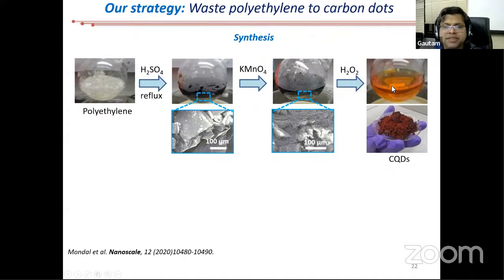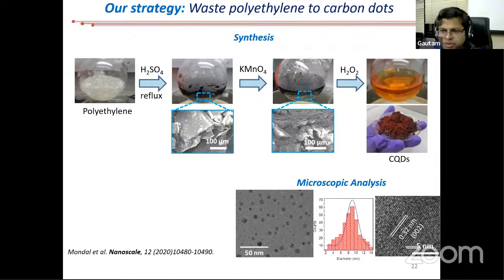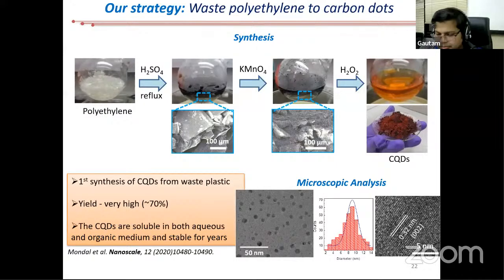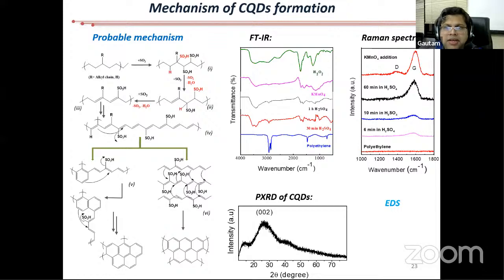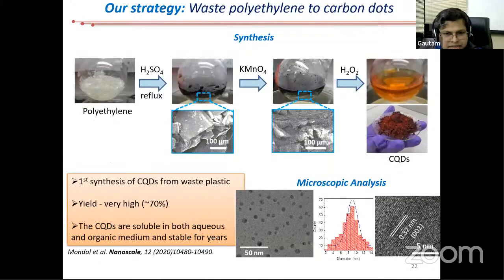It remains there. Okay, but you can remove it from there and you get these carbon dot particles in large quantities. And I showed you that this is about, say, 5 to 8 nanometers in size. And if you look carefully, in high resolution microscopy, you can see the graphite sheets here. The graphene sheets can be seen here. So we confirm that this is actually carbon dot. I will skip the mechanism part, because it might be slightly complex.